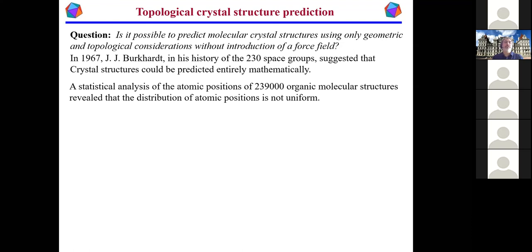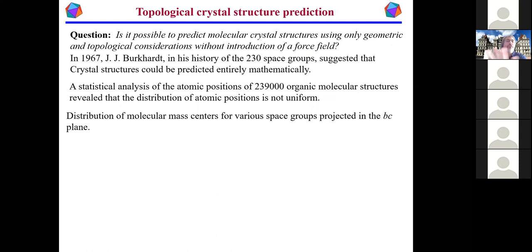Now, if you start to analyze these databases, so if you go through the COD, the Open Database, or the Cambridge Crystal Database, and you pull out, let's say, hundreds of thousands of these structures, and you plot, in this case, we took the centers of masses of the molecules in the different crystal structures. And we just did a heat map of where these centers of masses actually lie. Okay, so I'm going to show you a projection of the distribution that we got from mining the database along the BC direction. It turns out that these are the crystallographic BCs. If you do AB or AC, the results are pretty similar.